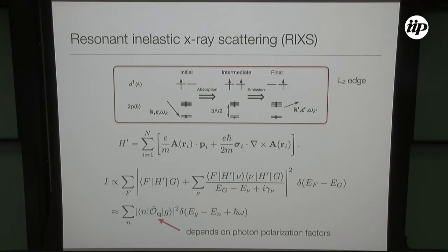And in fact, there is a way to probe different excitations, and that's resonant inelastic X-ray scattering, a kind of experiment that is becoming very popular for strongly correlated materials. This is essentially an experiment where you do scattering: there's a photon in, photon out response, and you treat the coupling to the electromagnetic field. The resonant in the name refers to the fact that you tune the energy of the incoming photon to coincide with the energy of a core hole that you create.